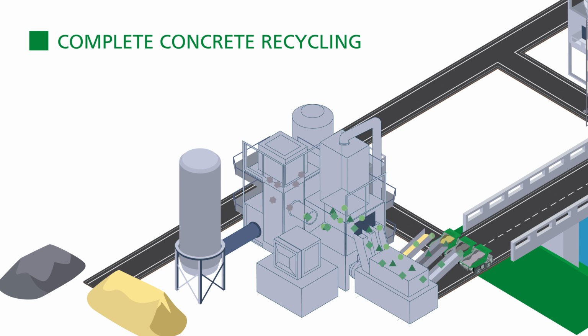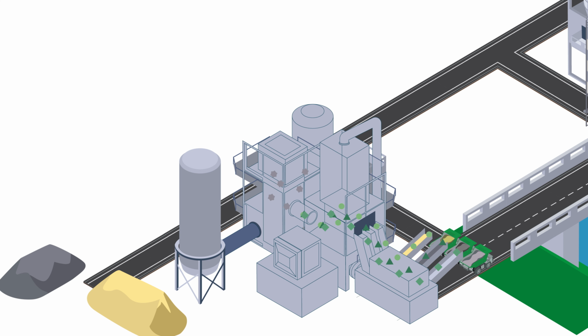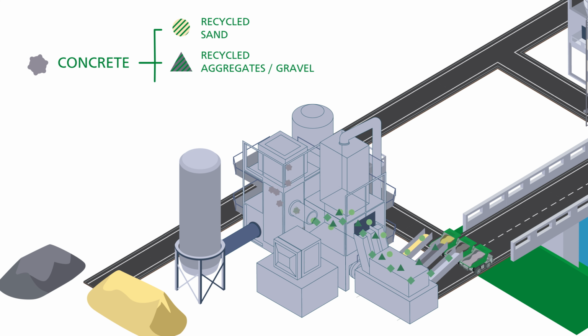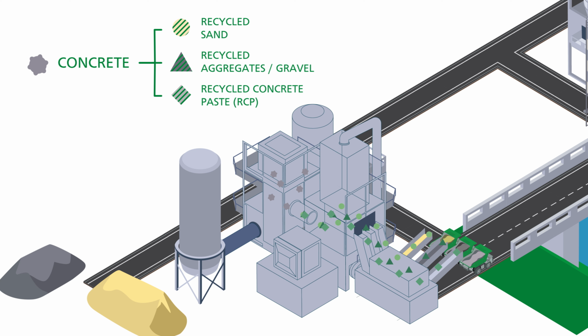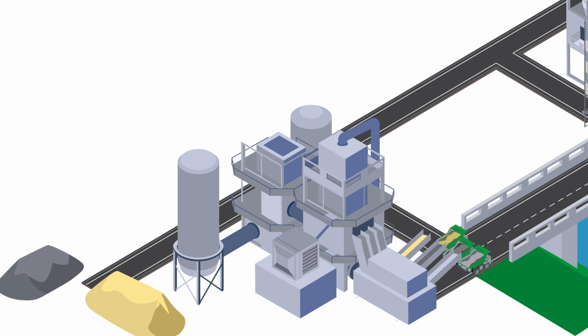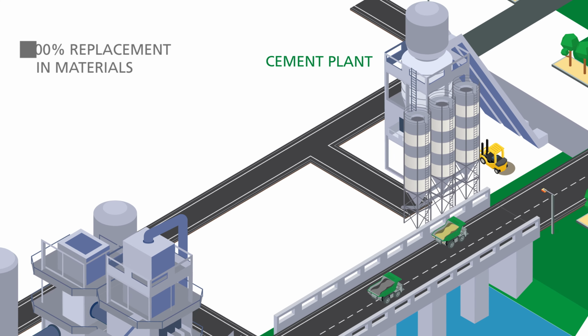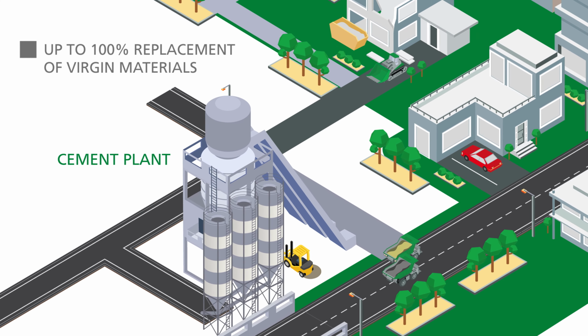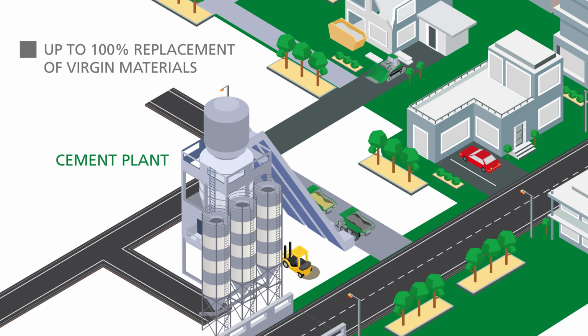New recycling technologies allow selective crushing and low-pressure grinding for efficient separation of the demolished concrete. In the recycling plant, the demolished concrete gets separated into sand, aggregates such as gravel, and what is called recycled concrete paste, or RCP. High-quality recycled sand and aggregates can replace up to 100% of their respective virgin materials in the concrete mix, without increasing the cement content or admixture dosage, and without impacting the workability or strength.